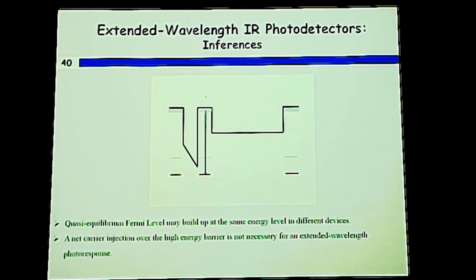to device, and it basically depends on the material property or the energy bands splitting up, and the buildup of the quasi-equilibrium Fermi level for the extended wavelength mechanism. So these findings will be very helpful for the next step, to design more efficient detectors. I'll show that later, but before that, I want to show you the results from the variation of gradient.